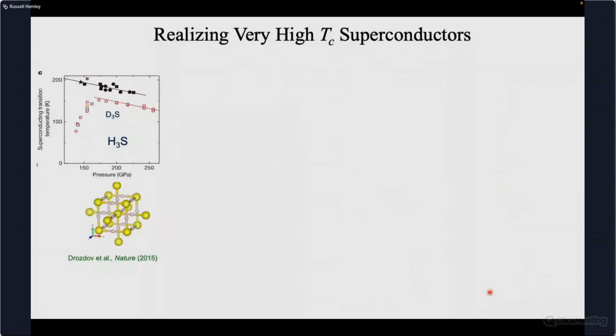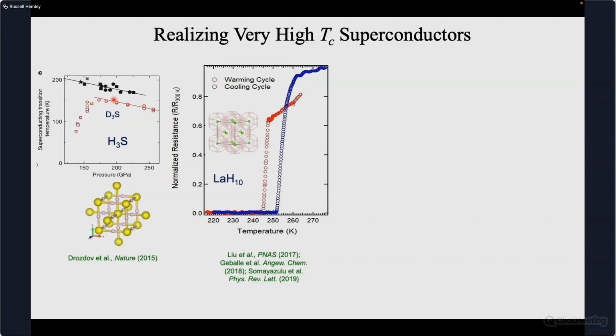So just a few comments on that. This was the important work of Mikhail Eremets' group, published in 2015, showing this beautiful structure confirmed by X-ray diffraction and this very impressive TC of close to 200 Kelvin at very high pressure. Also the isotope shift really is consistent with a conventional superconducting mechanism. So shortly thereafter, we focused on the lanthanides, because of the idea that they could liberate their electrons and generate very high pressure superconductors with even more hydrogen present.